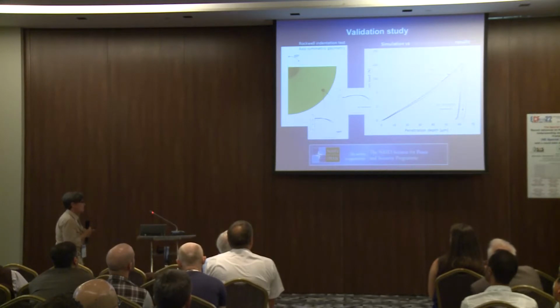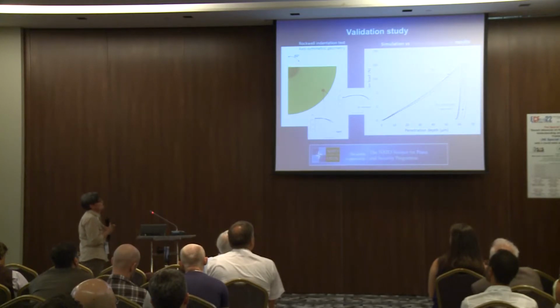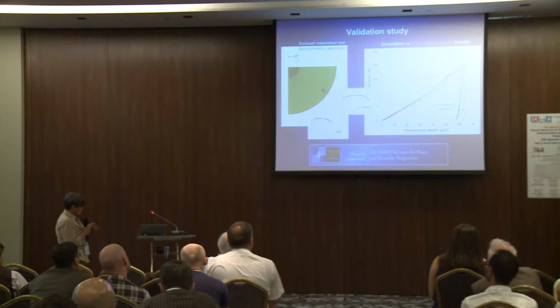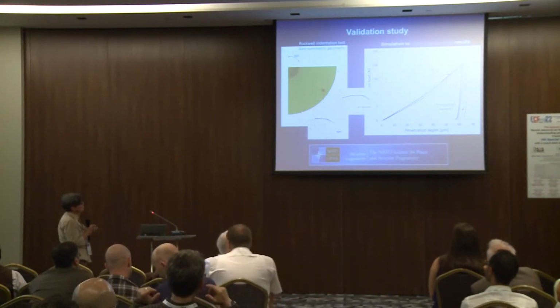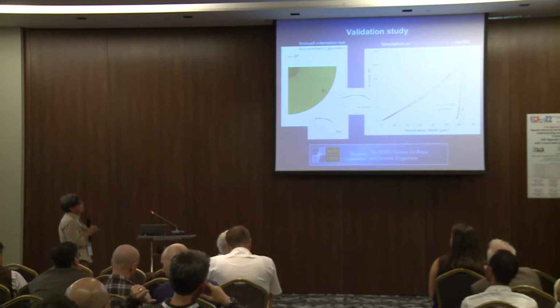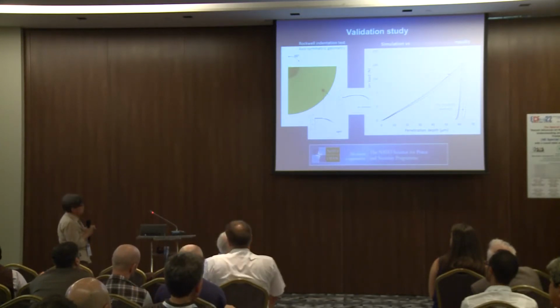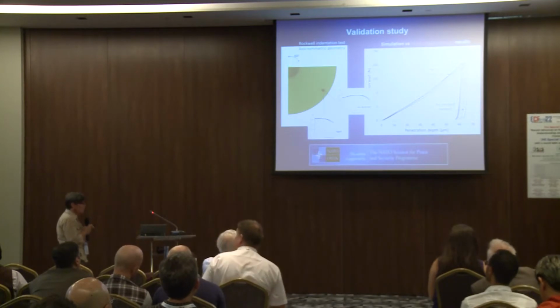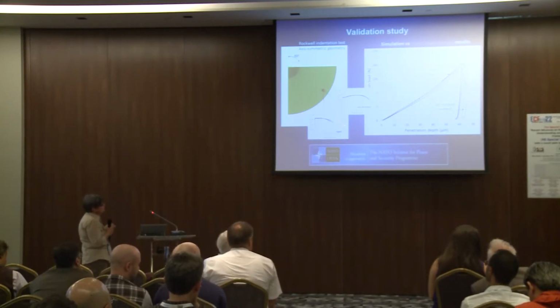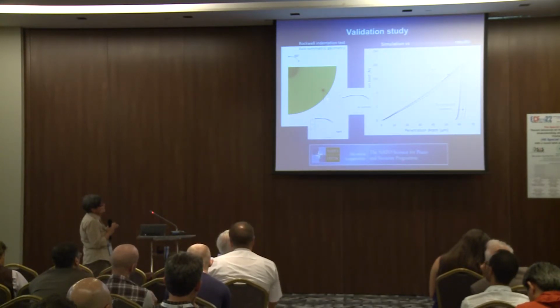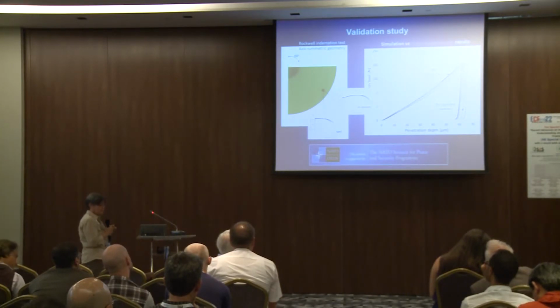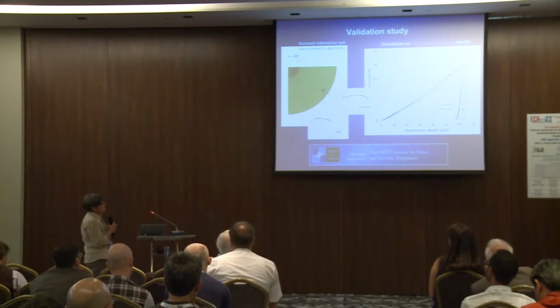The system becomes effective if we have a model which permits us to infer from this information the change of material properties, clearly without having to perform the uniaxial test contemporarily. So in our verification study, what we did so far was to build a finite element model of the test, similar to what we validated already in the former study, and then we performed a simulation feeding the material characteristics with the results which we obtained at a, let's say, macroscopic scale from the uniaxial test.